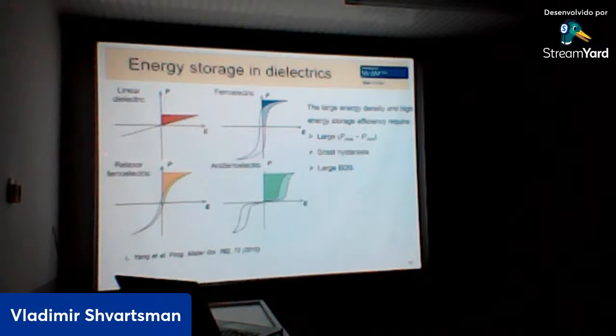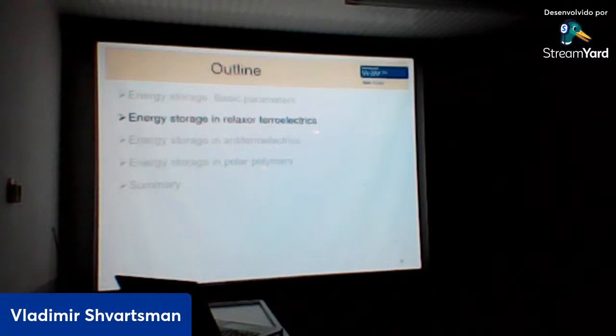materials families. One is the so-called relaxor ferroelectrics, which have large induced polarization, small remanent polarization, and also very tiny hysteresis, a very thin hysteresis loop. Or antiferroelectric material, which in the ideal case has zero or negligible polarization at zero field, against strong induced polarization here, and the area will be even larger than for the relaxor ferroelectrics, but they can also have large losses due to this finite hysteresis. In my next time, I will speak more about the relaxor ferroelectrics, antiferroelectrics, and polymers.